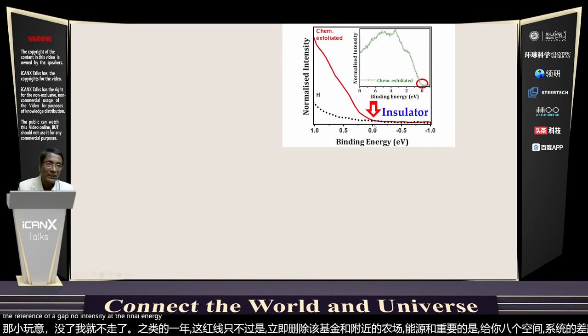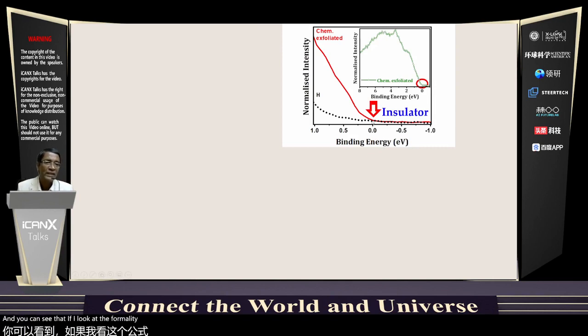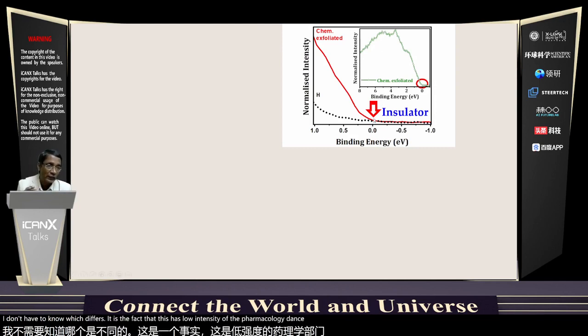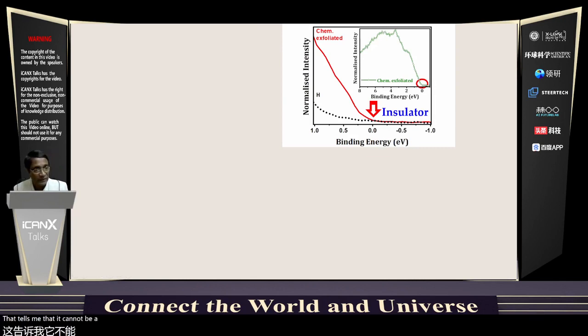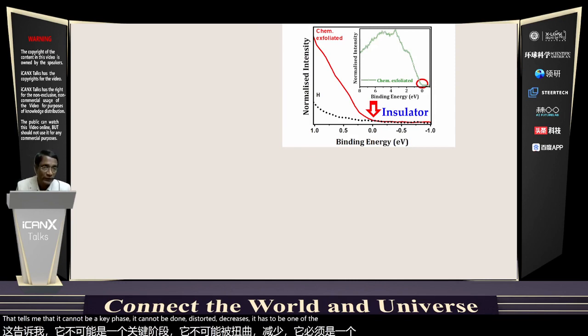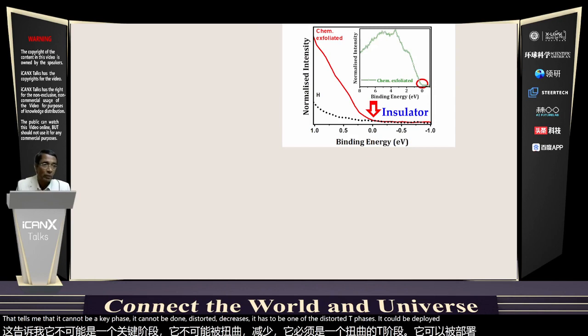And you can see that if I look at the Fermi energy, there is absolutely no intensity from my chemically exfoliated system. I don't have to know which T phase it is. The fact that this has no intensity at the Fermi energy tells me it's an insulator or a semiconductor. That tells me that it cannot be a T phase. It cannot be the undistorted T phase. It has to be one of the distorted T phases. It can be T prime, T double prime, T triple prime. So the question is which one it is and how do I figure that out?